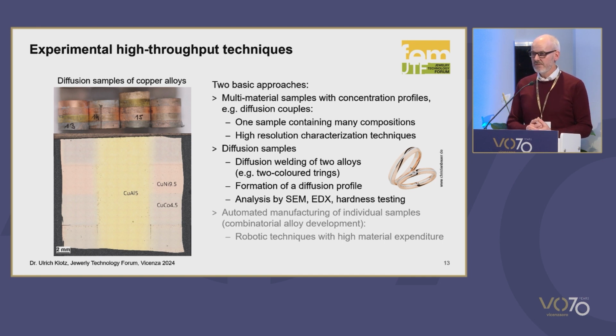And we are doing just the same, and this is an example that we did on copper alloys. So you see these samples in the top image. There are 4 or 5 rings, and you can see from the color that these rings have different composition. And in the lower image, you see the cross-section. So you see the 4 rings, and in the center there is a cylinder. And these rings and the cylinder are bonded together by diffusion bonding, so that they're in intimate contact, and so that diffusion can take place.